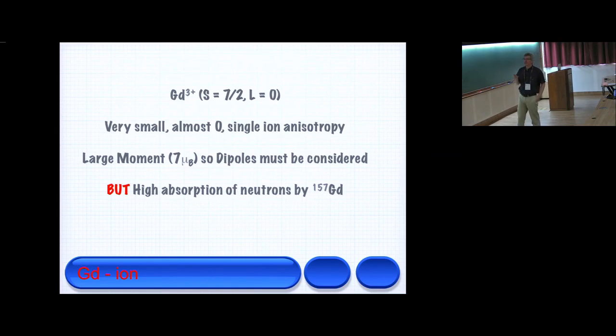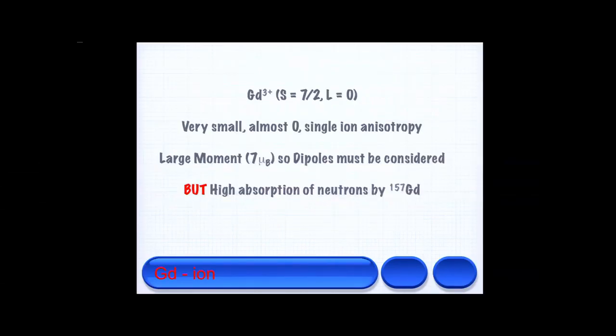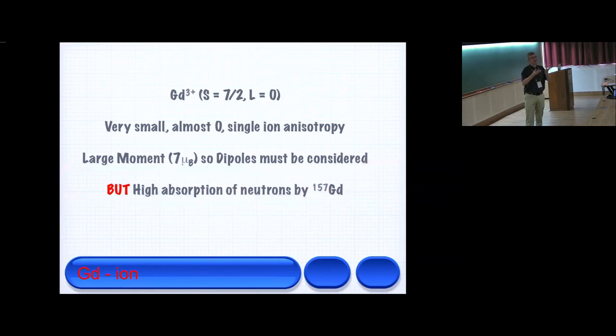And I started this because there was a Palmer-Chalker model out there where, like we chase spin liquid models, there was this thing that says that an antiferromagnetically coupled spin on a pyrochlore lattice, quantum or classical, will not order. All the models will show that if it's just a J, it remains a quantum spin liquid if you want. But if you have any perturbation from that, then it picks an ordering wave vector and you get ordering. And Palmer-Chalker, for things like gadolinium with a big moment and therefore dipole interactions, showed that there was this unique ordering for this quasi-Heisenberg system of gadolinium in the pyrochlore lattice.